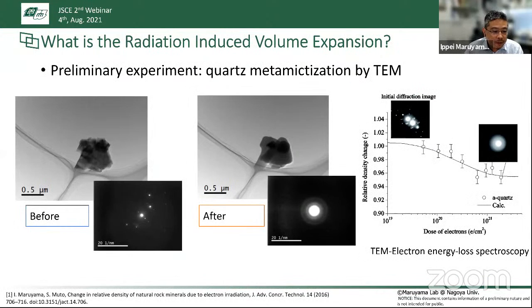By the way, do you know what causes the volume expansion of concrete under the neutron irradiation conditions? Concrete can expand because of the aggregate. This is a result of the metamictization of alpha quartz. Metamictization means that the crystal structure is destroyed by the radiation. Look at this picture. This is the transmission electron microscopy result of the alpha quartz. And this pattern is the electron diffraction pattern, which reflects the crystal structure of the alpha quartz. After several minutes of observation, due to the electron irradiation, the electron diffraction pattern disappeared.